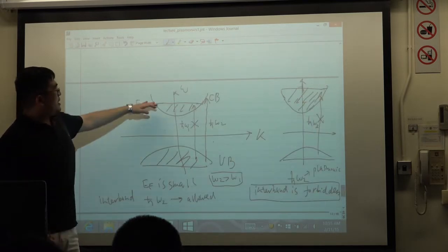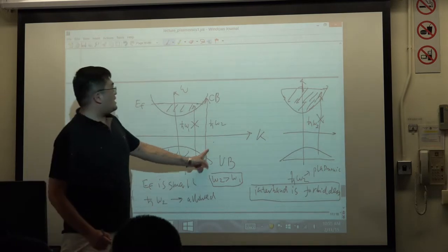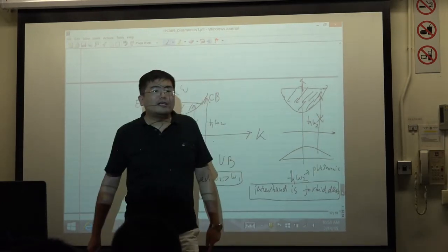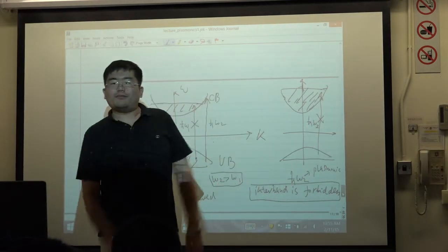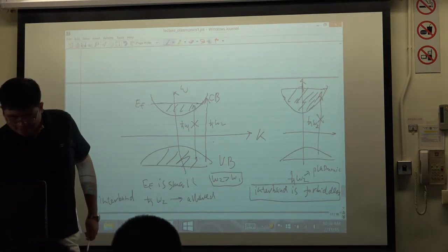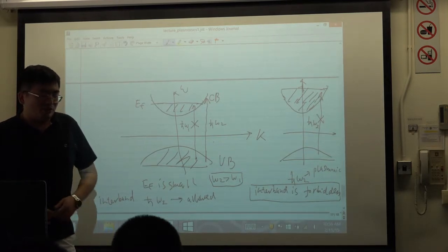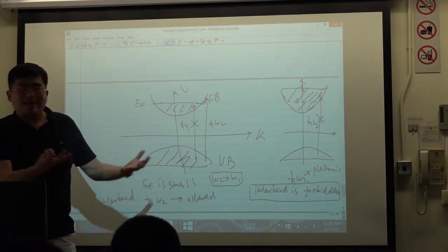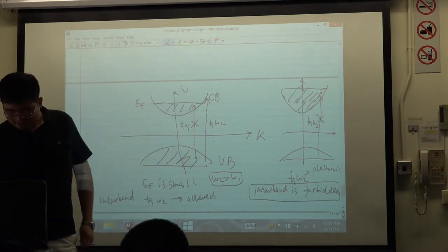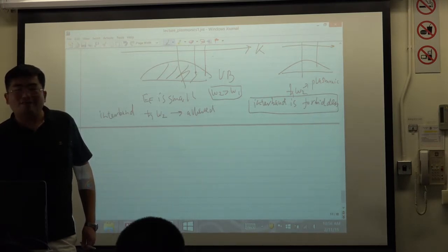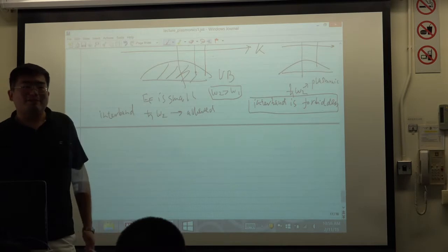For the lower Fermi level, at this h-bar omega there is no plasmonic effect because the Fermi level is low. Here there is a plasmonic effect because the interband transition is forbidden. This is why, for graphene, people apply a very high voltage to raise the Fermi level. They make this kind of plasmonic, called graphene plasmonics. For III-V materials like gallium arsenide, people use light to illuminate and generate many electrons to make this kind of plasmonic. But even so, it cannot reach visible light, because the Fermi level cannot be so high compared to metal.